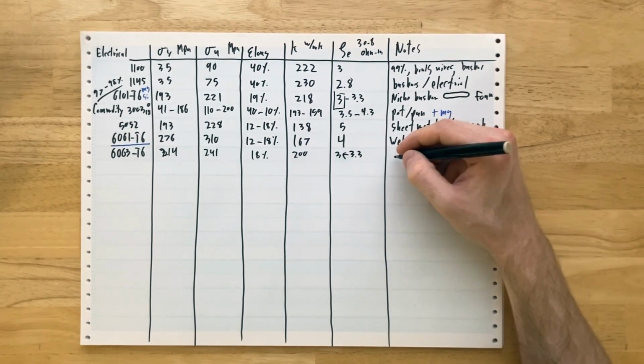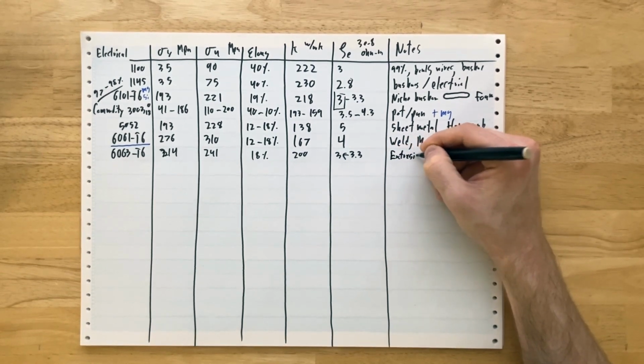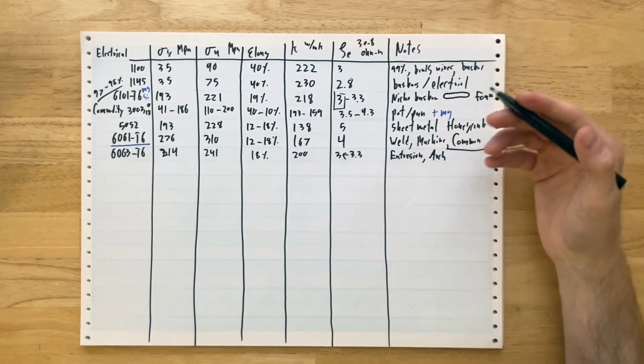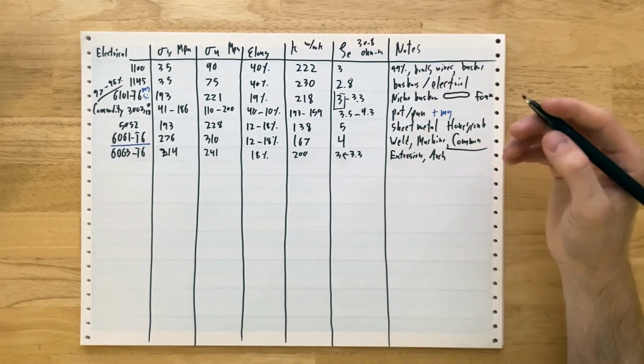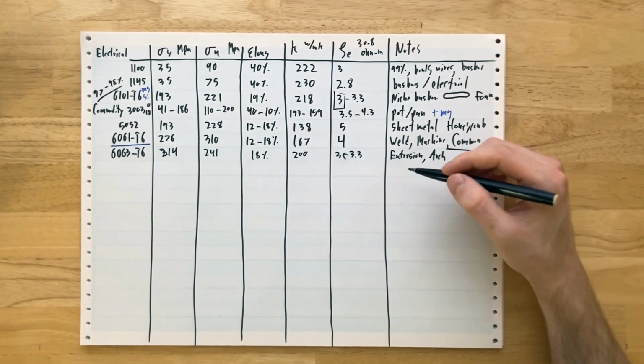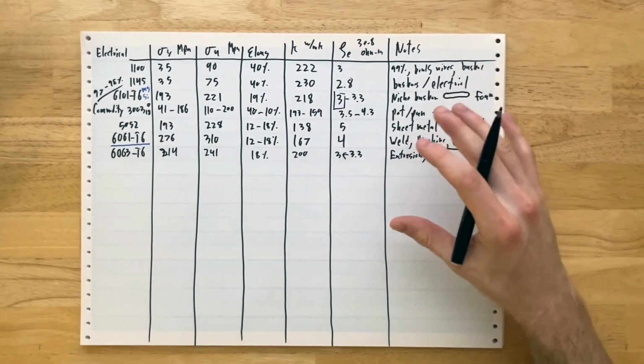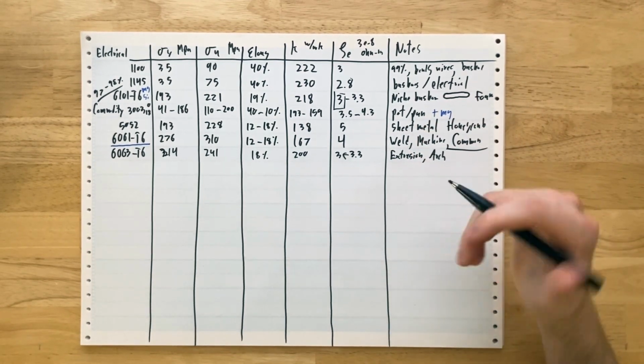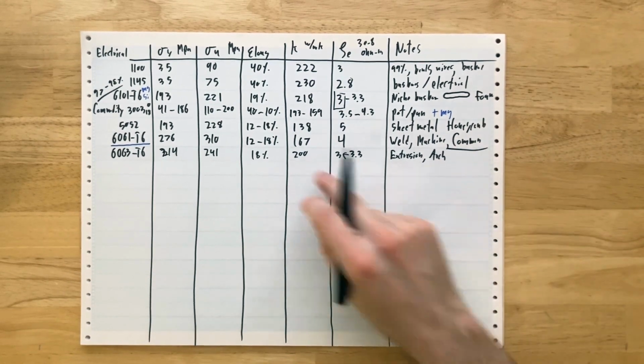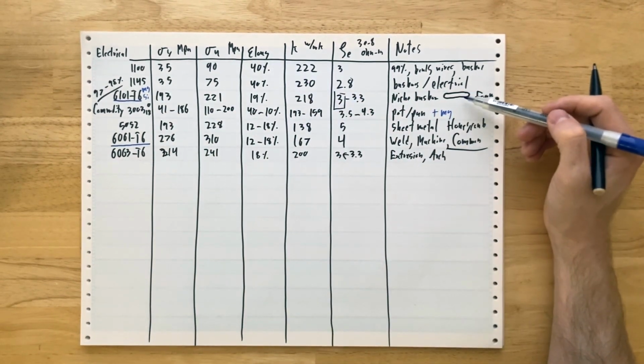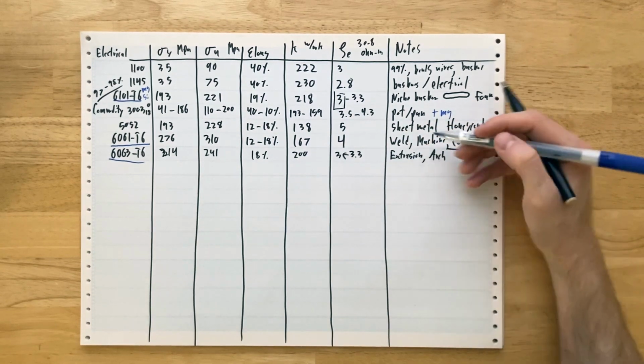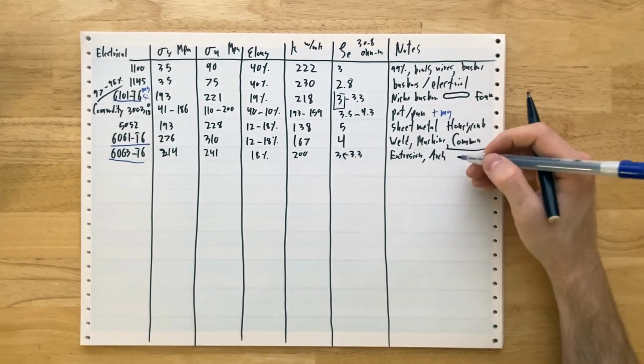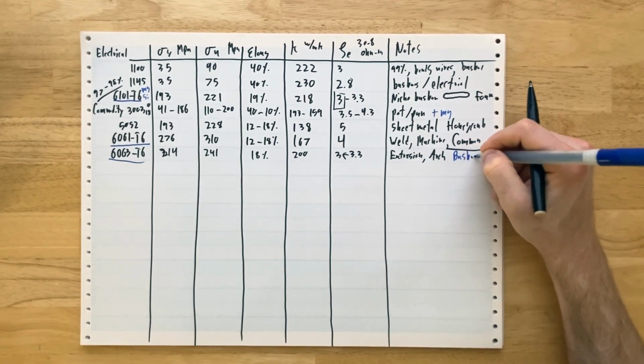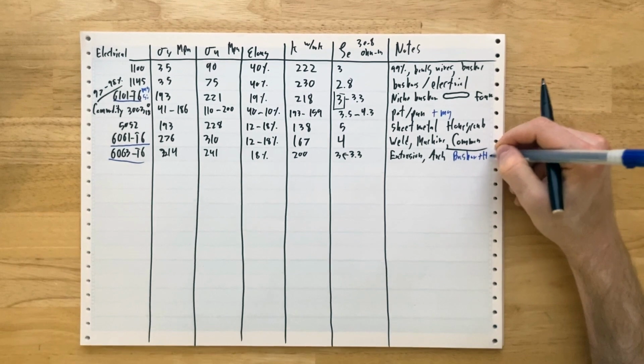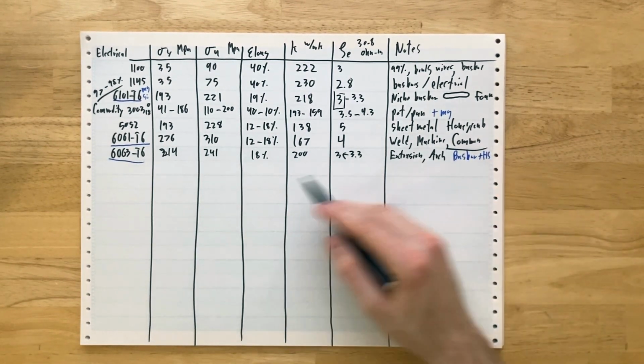So this is used a lot in extrusions. It's considered an architectural grade. If you ever see window glazings, they're extruded aluminum pieces. It takes anodization very well. It's corrosion resistant. But this is actually like a secret winner in terms of bus bars and heat sinks because it's very common. It has high strength and pretty good electrical and thermal properties. So if you can't get 6101 because it's only available in flat bar stock, you can definitely make your part out of 6063 T6. You can get it extruded, you can get it in billet, you can do all sorts of wonderful things with it. So this is a low-key bus bar material and heat sink material because of that combination. If you need to hold high pressure and move heat, really good place to start.